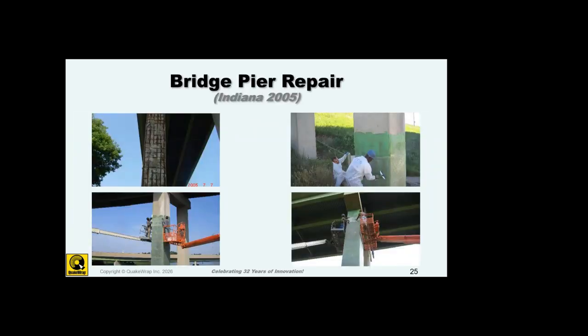Now, this is a 21-year-old job that we were doing with the old system in Indiana for Indiana DOT, and I wanted to point something out to you, how our new system is going to be so much better than this. So in this case, where the column of this bridge was corroded, the solution requires that you clean the rusting. You have to patch that deformed concrete, make it smooth, because you cannot apply the fabric to a rough surface. You can put it on a smooth surface only. So you patch that, then you have to wait for the patching material to dry. And then, as you see in the other photos, we wrap the fabric around the column, and that's how it has been done for decades now.